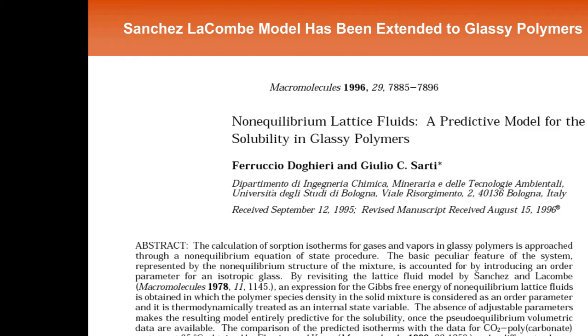The molecular motions can't reorganize the material so that it actually occupies the volume that it would want to occupy could it be in equilibrium. And depending upon how rapidly you cool it, you come out on a curve like this, or perhaps a bit higher or a bit lower depending on the cooling rate. And the material in this state now is not an equilibrium material, so it will not be described by thermodynamic theories that presuppose that the material is at equilibrium.